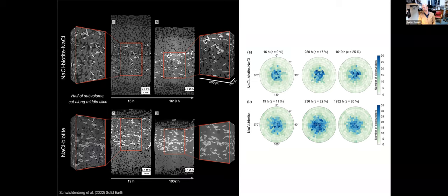what we were also quite surprised to find is that it doesn't rotate very significantly. There's no major rearrangement of the biotites in there. It doesn't happen. And that was highlighting that the dissolution process at the interface with the biotites was so effective that the halite never managed to point load. The analog that we used when we discussed this was to think of a hot stove and take an ice cube and try to exert pressure onto the stove. The ice will melt as it interfaces with the stove, right? So you'll never really be, it looked pretty much the same.